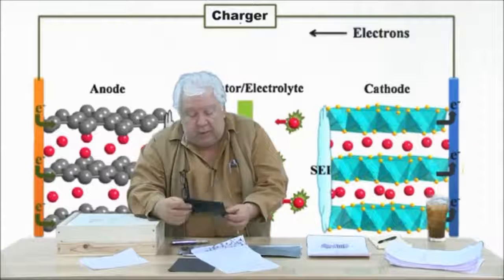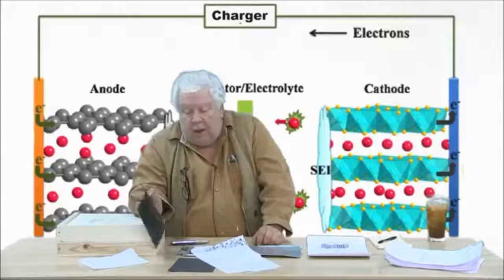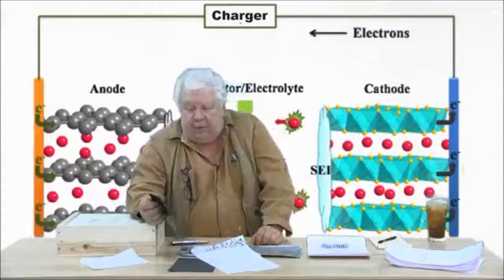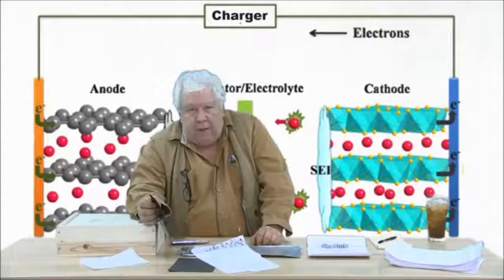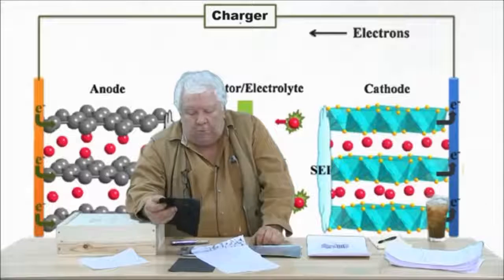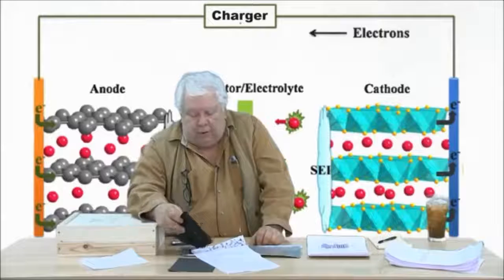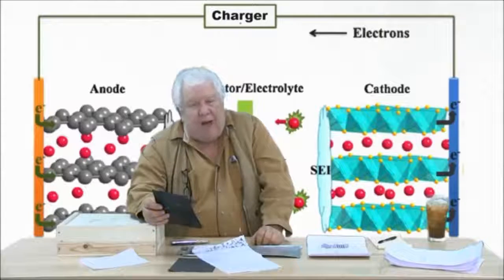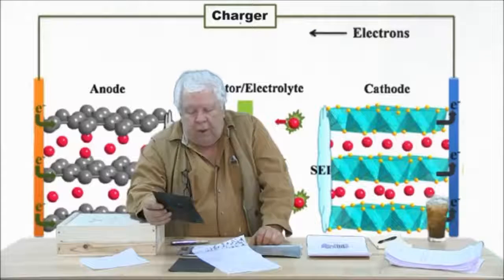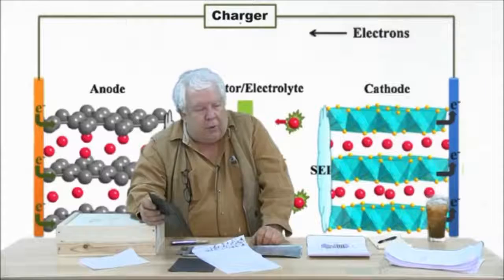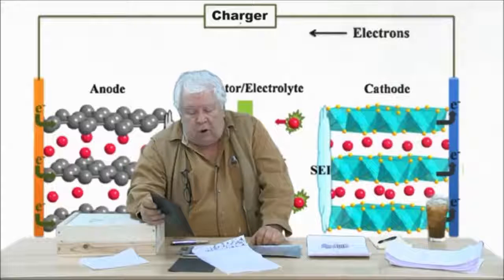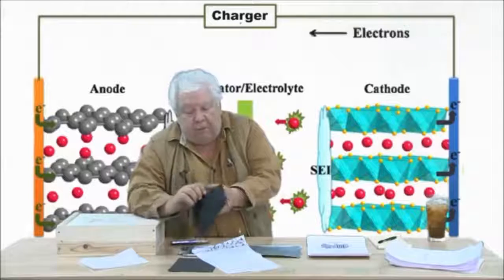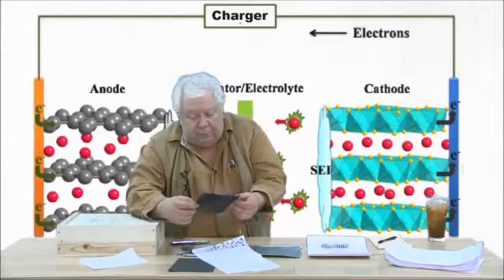Maybe some lithium plating on the other side. This is kind of shiny. Most of our cells aren't, but that is because lithium iron phosphate actually doesn't conduct at all. And so in order to get it to conduct and get a good current flow through the cell, they mix about 5% carbon in with the lithium iron phosphate. In the case of A123, they actually make a nanopowder granule of lithium iron phosphate and then coat that with carbon and make a slurry and put it on this aluminum foil on both sides